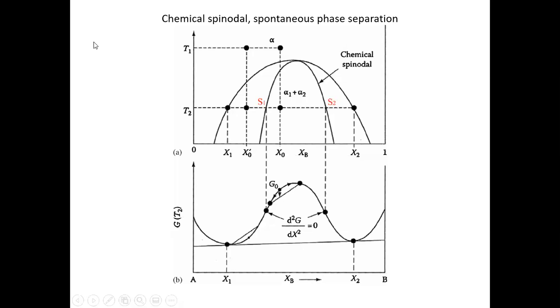But if you're, for example, outside the inner dome, there's still a possibility that you get stuck in this mixing state, although you want to be demixed. At least from the textbook that we're using, this is the notion that they define these things. But again, I'm not 100% sure that this is how the whole field uses it. Typically we just use the outer dome to define the miscibility gap, and the inner one is called the chemical spinodal, in which you have instantaneous instability. So that's what we agreed on, but feel free to correct me if you see people using a different notion in their own research.